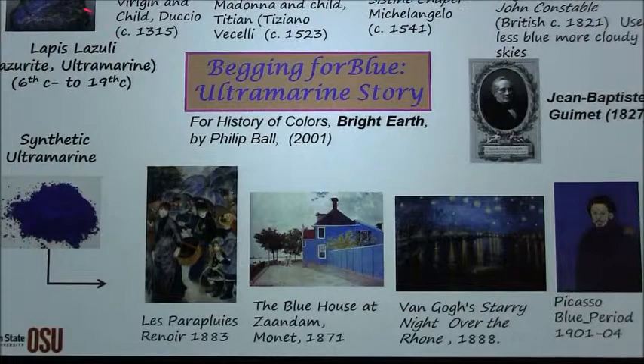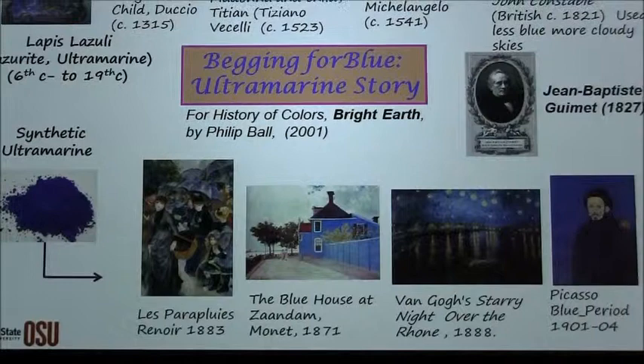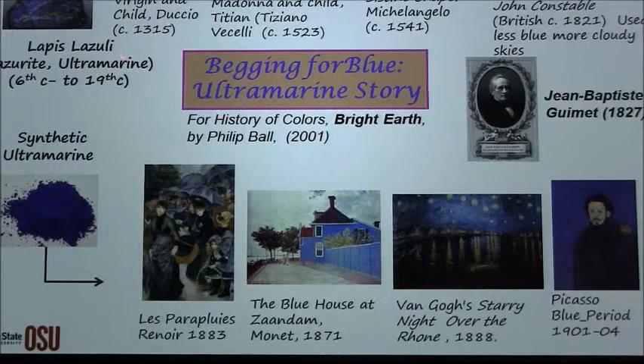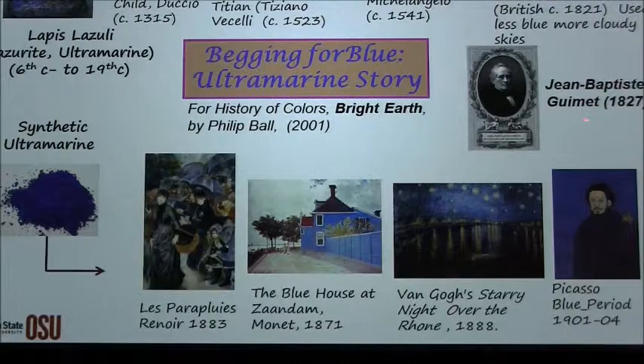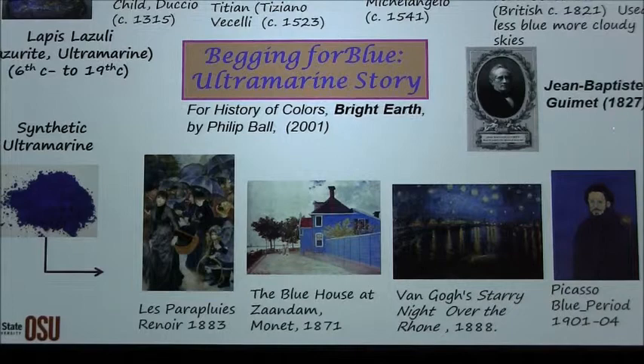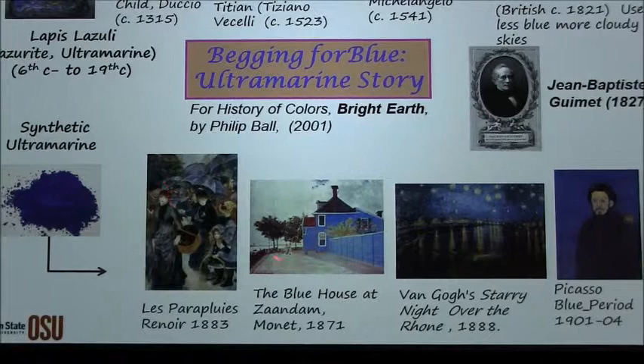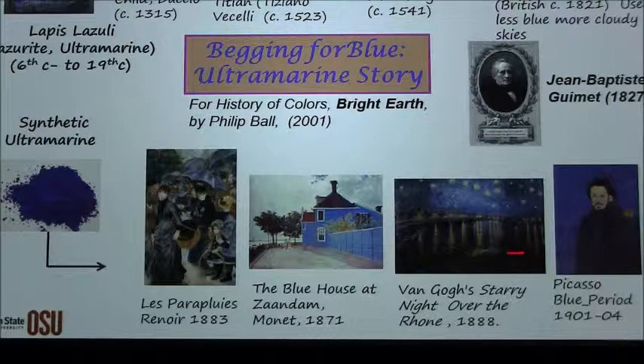See, at that time nobody knew the exact composition of lapis lazuli, because it doesn't have any transition metal like manganese or copper or cobalt. It's purely sulfur which gives rise to the color. Finally, in 1827, the chemist Jean-Baptiste Guimet successfully made an artificial pigment similar to lapis lazuli. Then it was used by Renoir and Monet, and even Picasso used a lot of this ultramarine blue for his painting, because we call it the blue period, which was painted by Picasso.